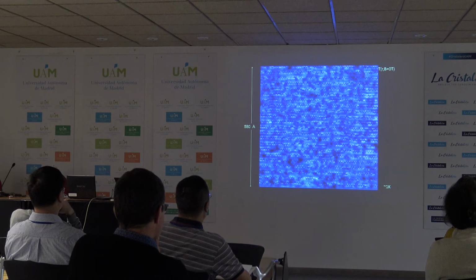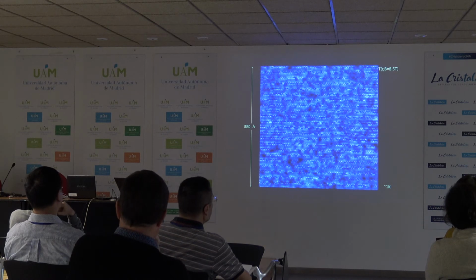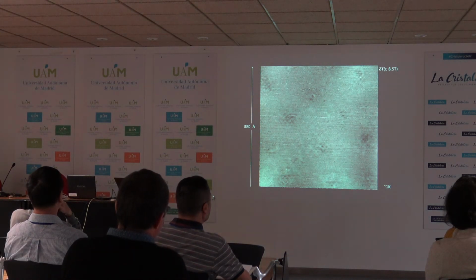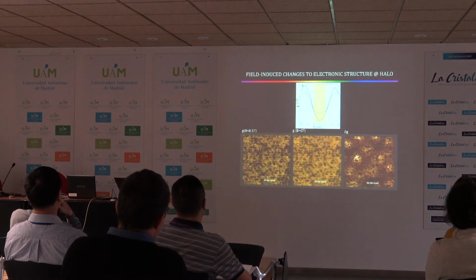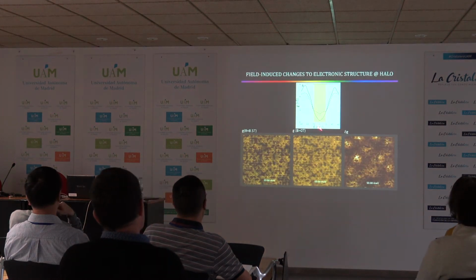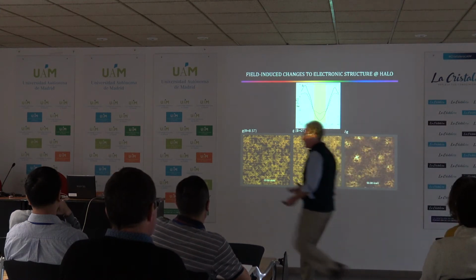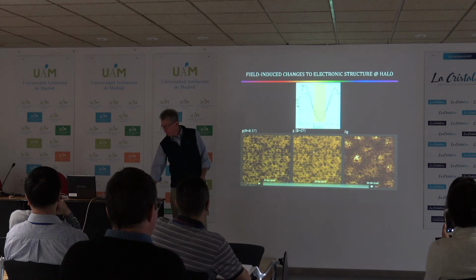So here's the image at high field in January. Now the experts in the audience can see that I'm not cheating, because there's an atom here that had moved during the month that they were in. Otherwise, all the atoms are registered within a few picometers. That means we can subtract. You have two images perfectly registered to each other, you're allowed to subtract them. In fact, we subtracted the density of states at high field minus the density of states at zero field to find the perturbation to the density of states from the magnetic field. That's what the right-hand movie shows.